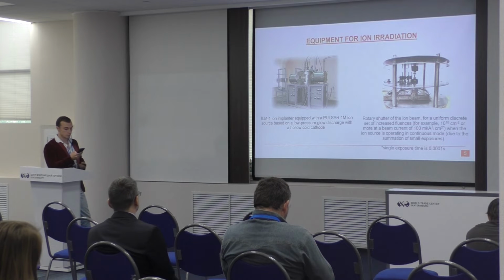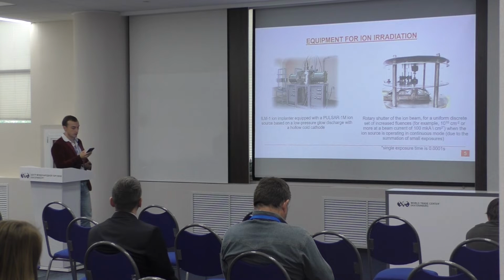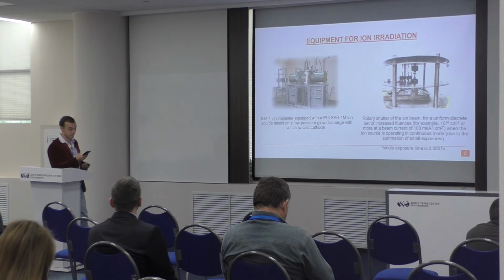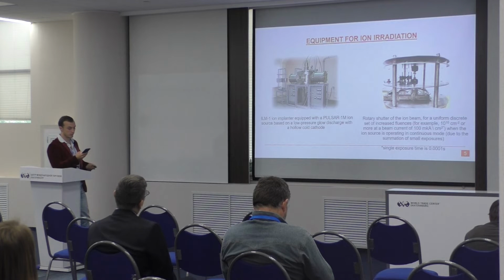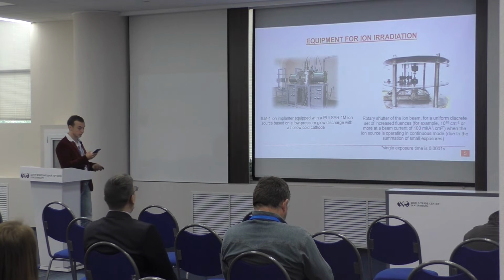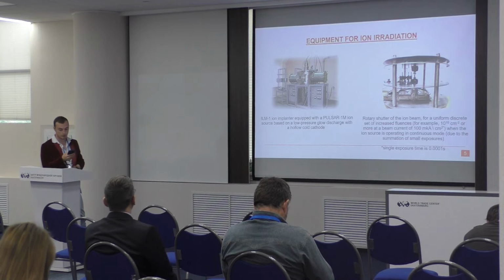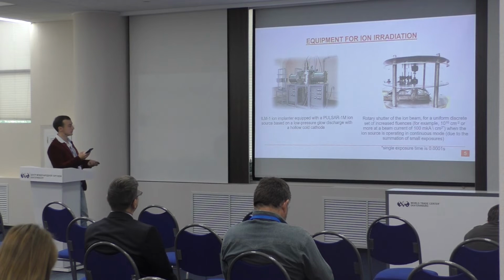This value was used because a number of studies in the literature have shown that ion radiation with low fluences can lead to an increase in the magnetoresistive effect. And we chose the fluence up to 10^17 to find the threshold values of fluences at which the GMR effect is preserved.